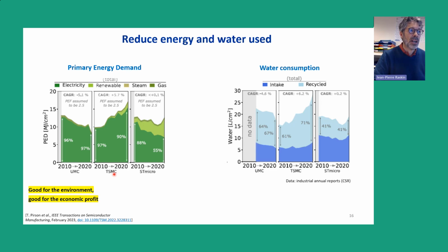I can just mention here three examples, three different companies, UMC and TSMC in Taiwan, and ST Microelectronics mostly in France and also in Italy. And this is data coming from the CSR, the Corporate Social Responsibility report. You can see here the primary energy demand and also the water consumption of those three companies. And then what we can observe here is a reduction, even if it's a low reduction, of the primary energy demand for ST Microelectronics and UMC. The same story for the water consumption for those two companies. This is good during this period of time, even if we see that the reduction is not really drastic.